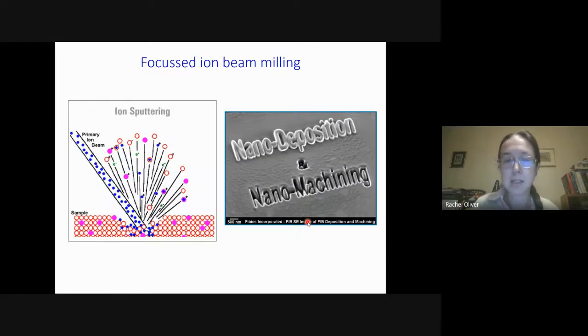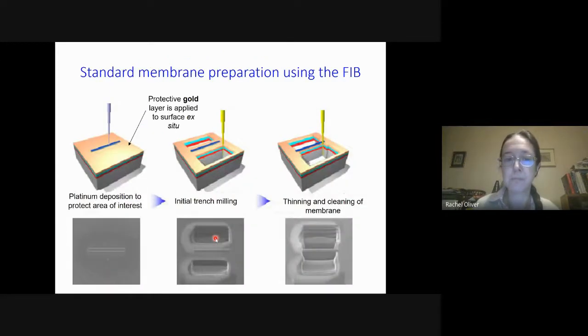And the way we decided to make this was using focused ion beam milling. So we have a beam of ions that we're going to use to either sputter away part of the sample surface, or we can also use it to deposit material. We introduce a metal organic precursor, which is decomposed by the energy of the ion beam, and then it's deposited on the surface. This FIB, or focused ion beam technique, is quite well known now. It's used for nanoscale prototyping, also very commonly for preparing transmission electron microscopy samples.